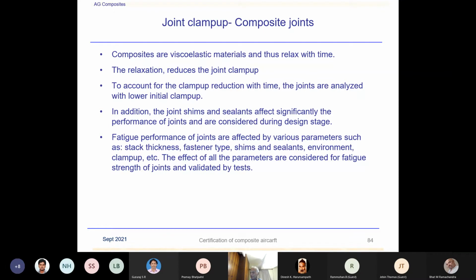However, when fatigue analysis is being done, fatigue joints are tested, and there's no analysis criteria available. In fact, fatigue life prediction for the bolted joint is difficult. You may have to determine some empirical relationships in order to determine the fatigue life, and that is based on the test data with various parameters. So coming back to the clamp up, the procedure to determine the fatigue life when we are doing the testing, we make the joint as per production procedure, and that is coupon with 100% clamp up, because that's what in production the aircraft will be delivered with. Even though we design with a lower clamp up, production has to be 100% clamp up, fully tight bolts.